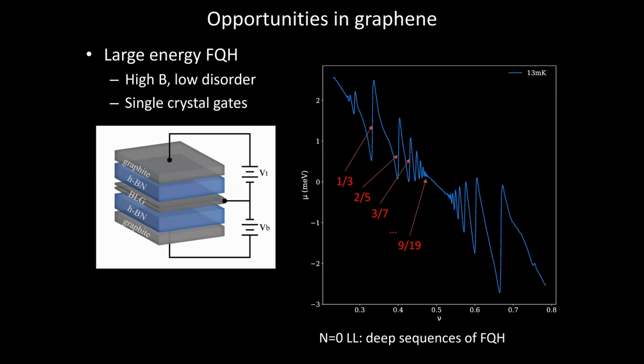So the opportunity in graphene is really twofold. One we've known for a long time, which is that if you study the fractional quantum Hall regime, for example, you have a very clean system. You have practically infinite control of the carrier density. And so you can study things at very high magnetic fields where the energy gaps of these fractional quantum Hall phases are very large, several milli-electron volts. That's actually a very big energy scale for fractional quantum Hall physics. It's easy to do experiments in the limit where this is a big energy scale compared to temperature, disorder, and so on. And we've done this by making our entire heterostructure out of graphite and boron nitride,